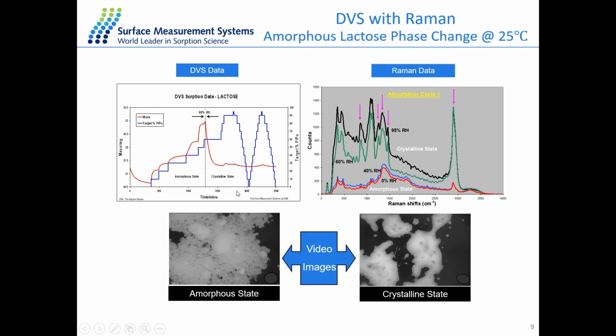An example with the DVS with Raman spectra. On the left-hand side is our DVS data. We used an amorphous lactose sample at 25 degrees. We change the humidity from 0 to 90% RH, which is the blue line here, and the red line is the change of mass for the sample. At each humidity step, the sample picks up moisture, reaches equilibrium, and then jumps to the next stage automatically.